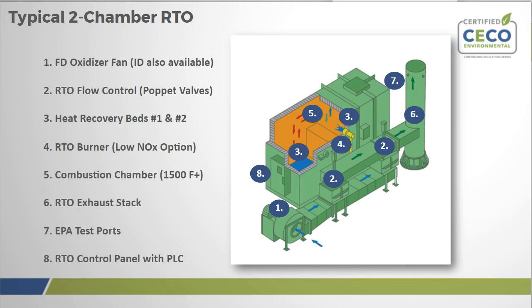It does require a split second of flow reversing, which in the case of this two bed allows VOCs to actually bypass the combustion chamber for that split second and escape straight through the stack. So you have the process fan, and then for a split second while these two valves at points 2 are switching, the process essentially goes from that bottom duct up to the top duct and out the stack for about a half second. This is why, in part, the RTO is typically rated at a minimum of 98% destruction efficiency, but there are things you can do to capture or mitigate that puff entirely so that it's over 99% effective like the other straight-through designs.